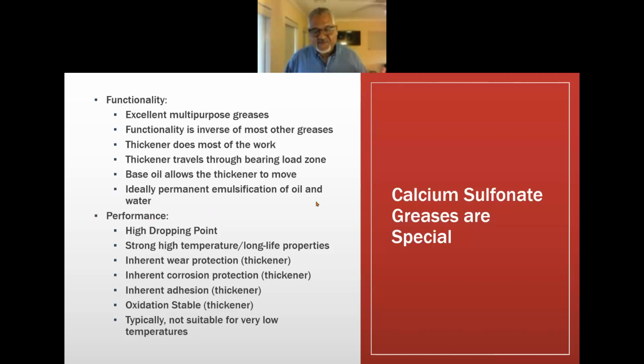So as I said, in conventional greases, the base oil does the work. With calcium sulfonate greases, mostly the thickener does the work. You can slow down the thinning effect due to high temperature with different base oils in a calcium sulfonate grease, yes. But most of it works from the thickener. Performance-wise, you get a higher dropping point because the thickener holds on to the base oil. You get strong, high temperature, long life properties because of the stability of the thickener.